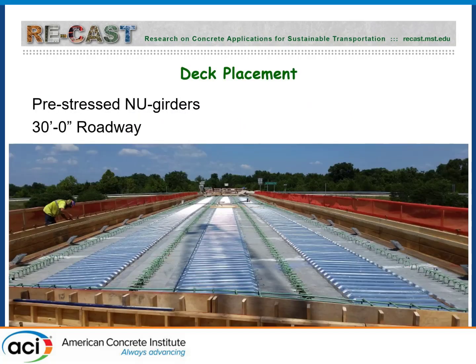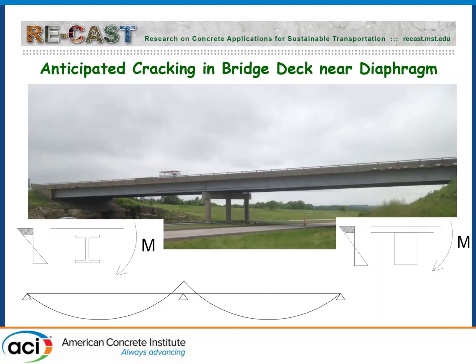So the next step was the fun part, to go to the job site and try to implement this quite new concrete with job site conditions. We did this in Missouri in the summer, not a very friendly construction environment, it's pretty hot. But you can see here the roadway, so this is 30 feet wide and two spans, about 120 feet each, with pre-stressed girders. And as expected, in the middle where you have the diaphragm, this is where the casting actually started, and then it went above to the bridge deck.